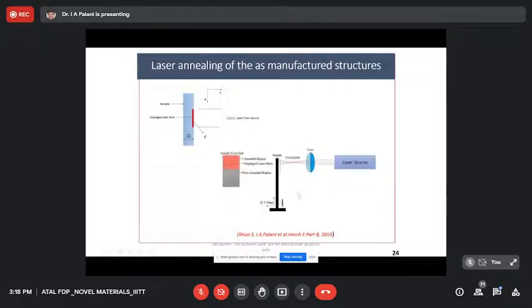In the case of laser annealing, what we did is, we used a laser to scan through the entire sample, back and forth, and the scanning was done in such a way that there is a continuous overlapping which happens. There is a 50 and a 90% overlapping we went, so that we try to crystallize the entire area using laser annealing. So this is a block kind of structure.